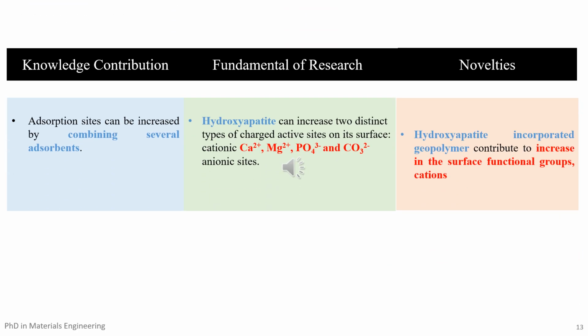So, the knowledge contribution of the study is that adsorption sites can be increased by combining several adsorbents, and the fundamental of the research is that hydroxyapatite can increase two distinct types of charge actives on its surface, namely cationic calcium and magnesium, and anionic phosphate and carbonate. The novelty of this study is that hydroxyapatite incorporated geopolymer contributes to an increase in the surface functional groups and cations.